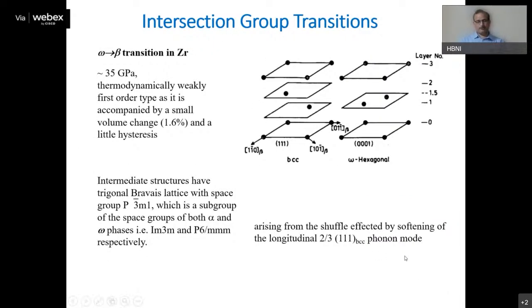Now let us come to another example, which is an example of the intersection group. This is the famous omega-beta transition in zirconium. This happens under pressures of about 35 GPa. This is understood in terms of the collapse of these two planes. If you take a BCC phase along the body diagonal, you have atoms sitting like this. As soon as it goes to the omega phase, you can consider these two planes collapsing onto the same plane. Now this atom basically lies on this plane, which is at the midpoint of these two planes.